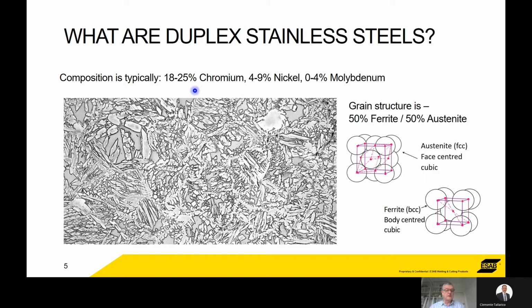The composition of the steel, typically for duplexes, anything up to 25% chromium, 9% nickel and 4% molybdenum. Each of these alloys has an effect on the properties of the stainless steel. They're there for a purpose, but the duplex is not just because it has this combination of these alloys, it's the way that it's manufactured. And the way that it's manufactured is to make benefit of generating the austenite and ferrite balance.